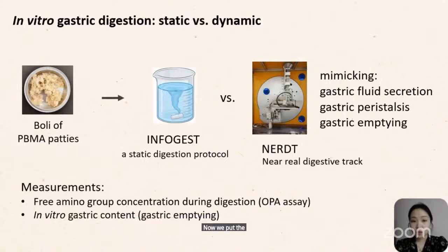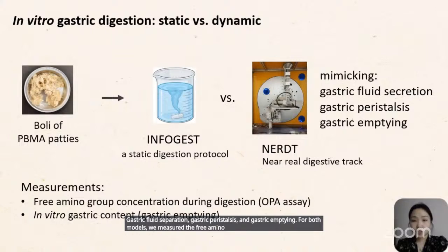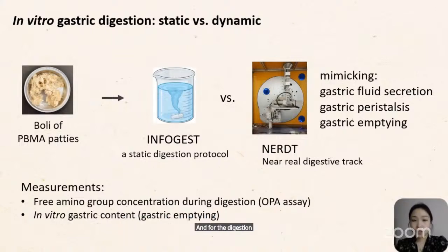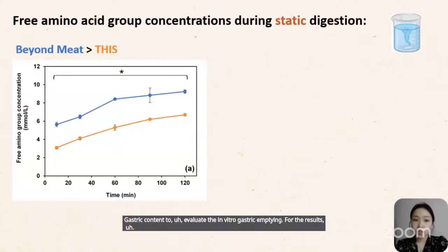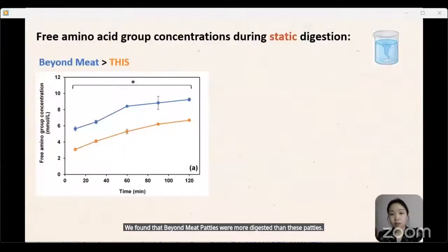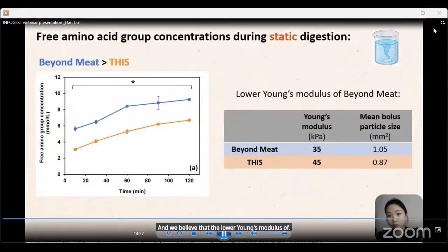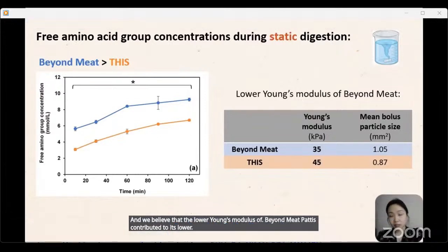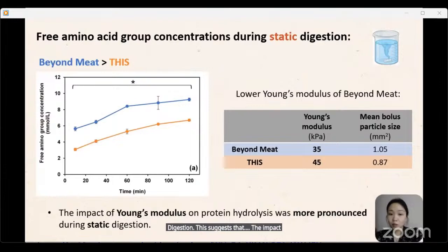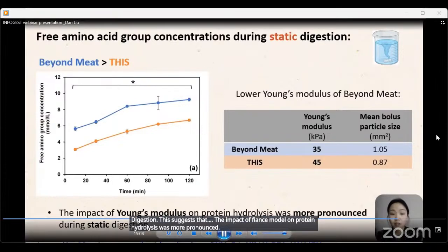Now we put the boli of these 2 patties into a static model and a dynamic model which can mimic gastric fluid secretion, gastric peristalsis, and gastric emptying. For both models, we measured the free amino group concentration during digestion, and for the dynamic digestion, we also measured the gastric content to evaluate the in vitro gastric emptying. For the results, for the static digestion, we found that Beyond Meat patties were more digested than the other patties, and we believe that the lower Young's modulus of Beyond Meat patties contributed to its higher digestion. This suggests that the impact of Young's modulus on protein hydrolysis was more pronounced during static digestion.